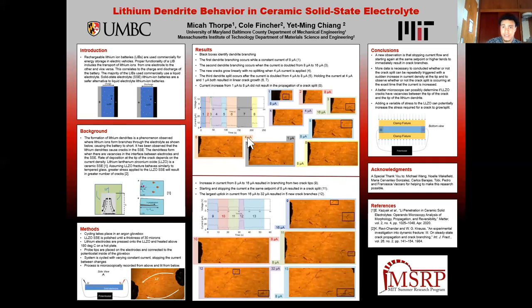They do continue in the next section for figures 9 to 13. But we did not see a crack split when we applied 8 microamps in figure 8. On figure 9, we jumped from 8 microamps to 16 microamps, and we see a 3 split in the bottom, and at the top of the image, we see a 2 split that's further visualized in figure 10 when we drop the current to 8 microamps.